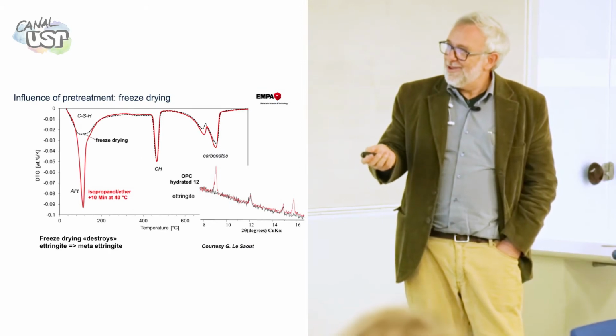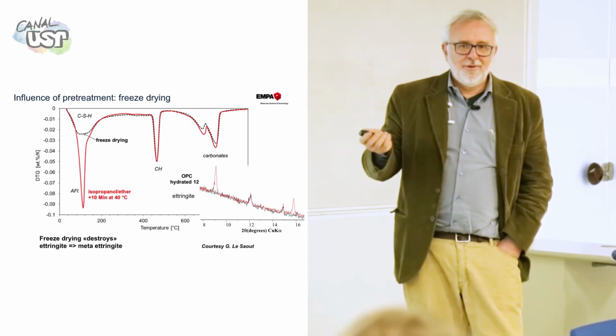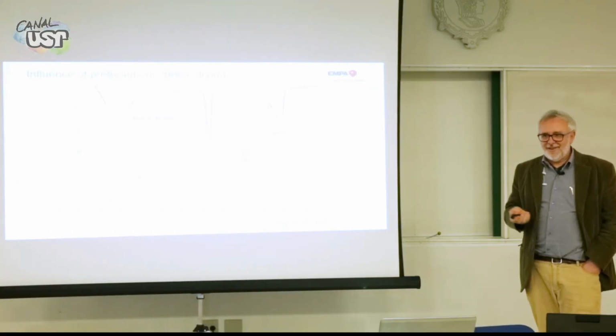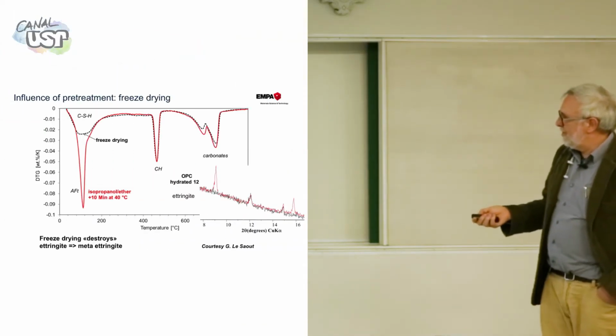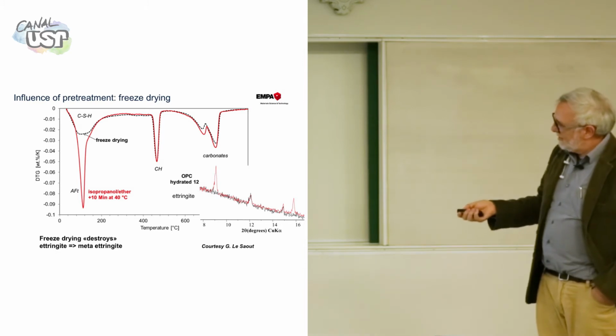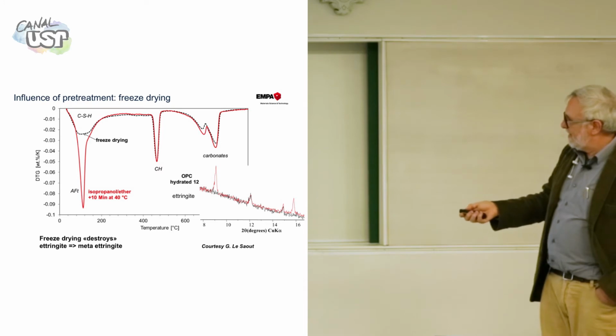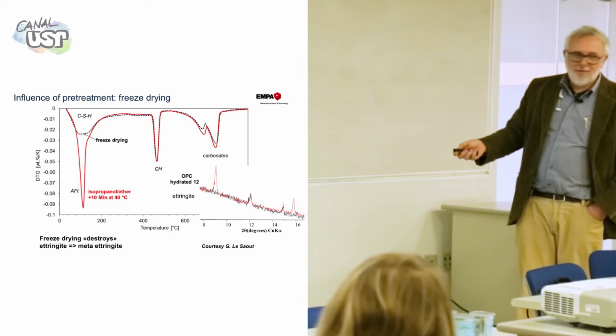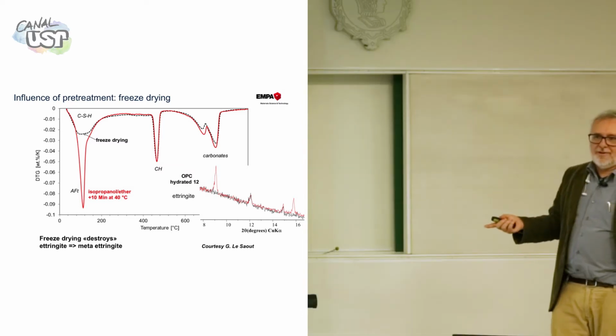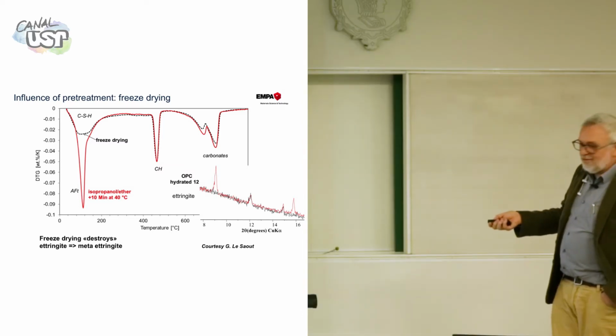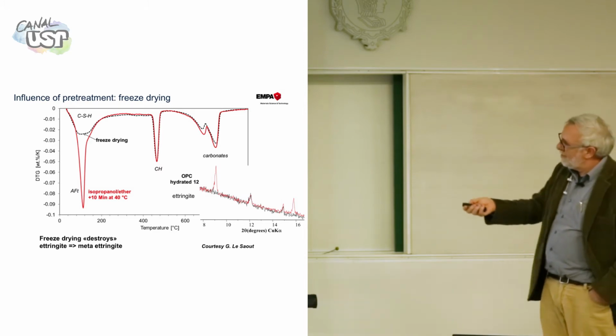So you can use freeze drying, but you lose information regarding CSH and ettringite. So it's a completely different peak. We use it a lot, freeze drying here. And then nowadays we are getting more beautiful peaks. Yeah. So we lost information on the time. And as Karin showed before, when you do freeze drying, this is XRD, and you see the baseline going up. This is ettringite. Ettringite disappears. And this is monocarboaluminate, a reaction between the limestone and the cement hydrates. So you lose it all. And of course, if you lose it here, you're going to lose it here.